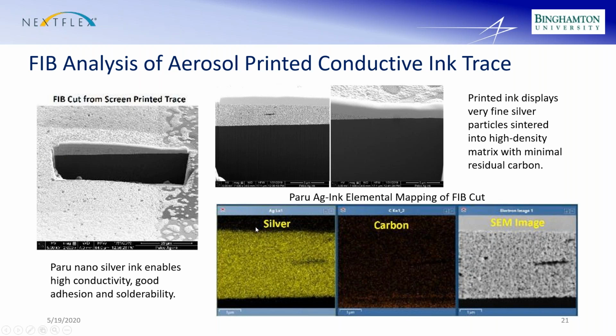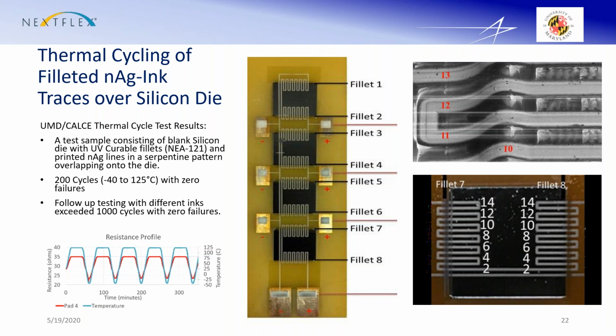But when you look at the structure in this FIB cut, the nanoparticles, in this case silver nanoparticles, form a really nice, fine, high density matrix. That's what gives you the high conductivity compared to something like an inkjet or a screen print or some other dispense technique. You get a really nice, fine structure with very little impurities. So we understood where we were going with it and what we wanted.